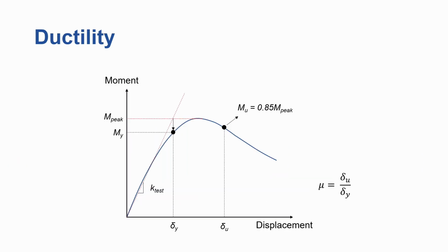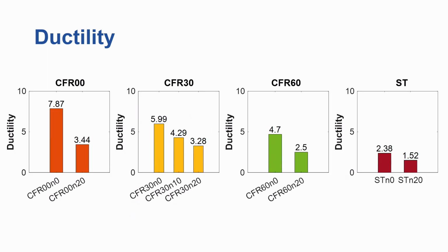And then we looked at the ductility. So this was taken as the ratio of the ultimate displacement to the yield displacement. And the ultimate case here was taken as a drop in moment about 15% from the peak moment. And then we noticed that as the axial load level increased, the ductility in the members reduced, which makes sense. But then we noticed that as the rubber content in the concrete increased, the ductility still reduced, indicating that those square tubes didn't really benefit that much from the rubberized concrete infill, unlike what is commonly reported for circular sections infilled with rubberized concrete. And we do think that this is mainly because of the lower confinement that the square tube section imparts on the infill concrete.